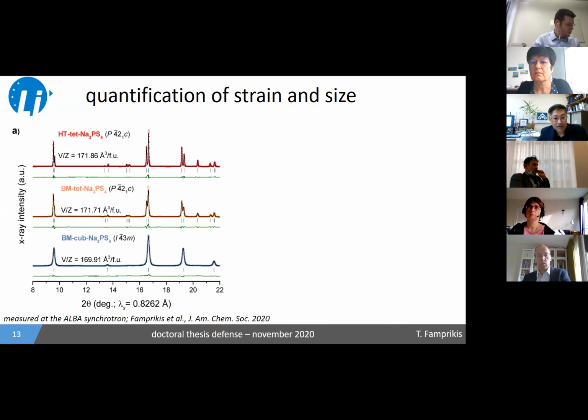So let's first have a look at the diffractograms. You will recognize the tetragonal phase through these distinct peaks and doublets. So we get the right material from solid state synthesis on the top. From ball milling, we actually get the cubic polymorph. Again, you see that the peaks denoting the tetragonal phase are not there, and the doublets have now merged. And the intermediate synthesis also stabilizes the tetragonal phase.